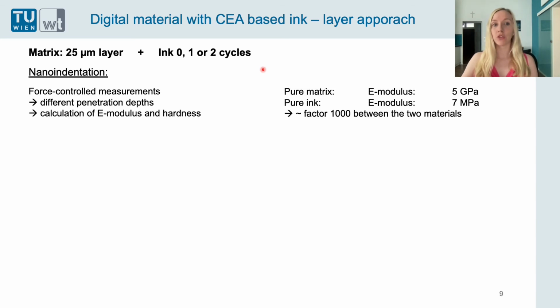And nanoindentation measurements of this printed material were conducted, and here force controlled measurements were done because you have a fixed force, and then you get different penetration depth depending on the material, and out of this penetration depth the software can calculate the E-modulus and the hardness of the material. So in the following I will only compare the E-modulus because both show the same trend. And you can see first the pure materials were measured. So the pure matrix has an E-modulus of 5 gigapascal, while the pure ink has an E-modulus of 7 megapascal. This means there is nearly a factor 1000 between the two materials.